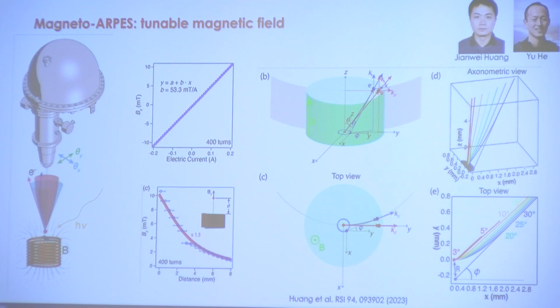Basically, you can imagine that if you have an out-of-plane field, the first order of business is a Lorentz rotation. The electrons that enter the analyzer slit will look like they're rotated. So he did a bunch of simulations to look at the rotation for different emission angles. Emission angle is the angle at which the electrons come out of the sample. You can see that they rotate in a parallel fashion, which means that the entire Fermi surface, no matter which emission angle you have, basically rotates together.